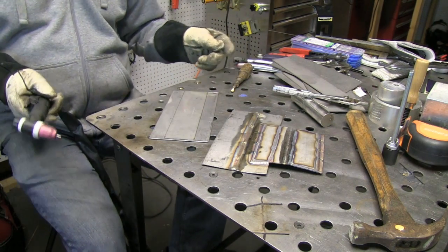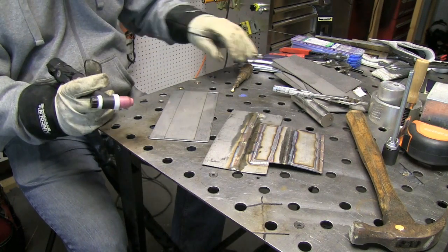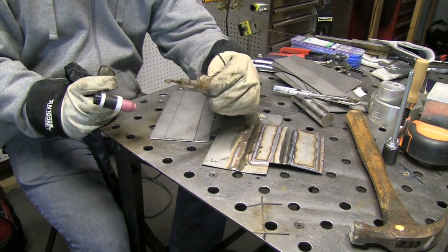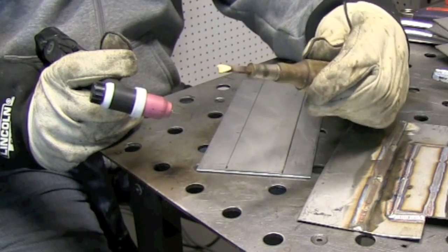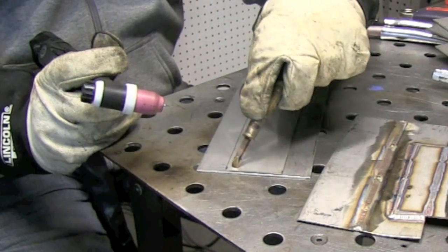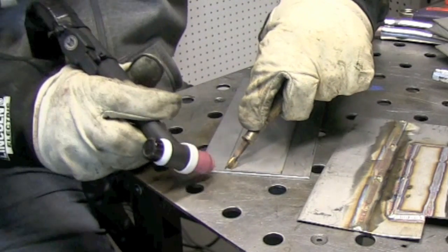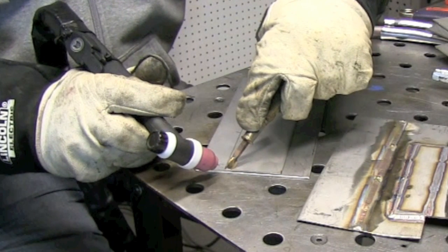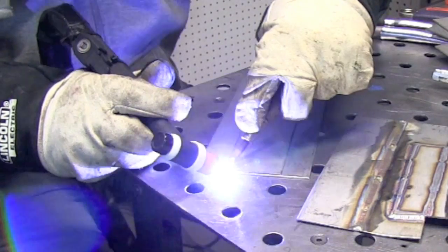And in order to get a good fit up, you can use a little homemade tool like the one I have here. It's just an old screwdriver with some silicon bronze weld metal welded on the end and then sanded off to where there's kind of like a little angle on it. And I place that right next to where I want to put the tack, put pressure downward, and set the amperage to what I'm going to weld at. And then I go full pedal pretty quickly to get that first tack.